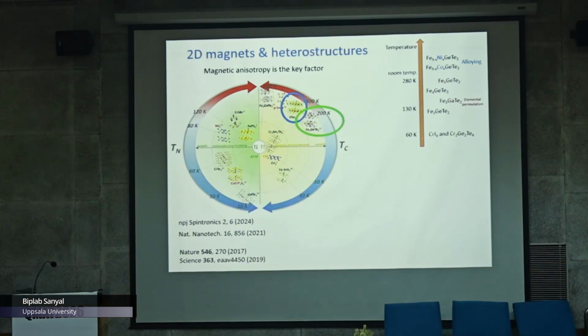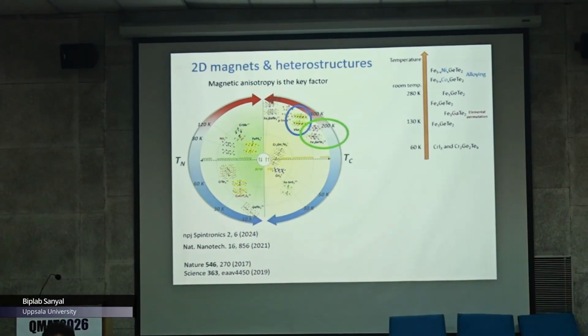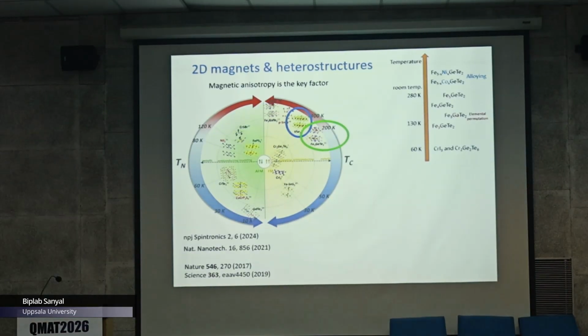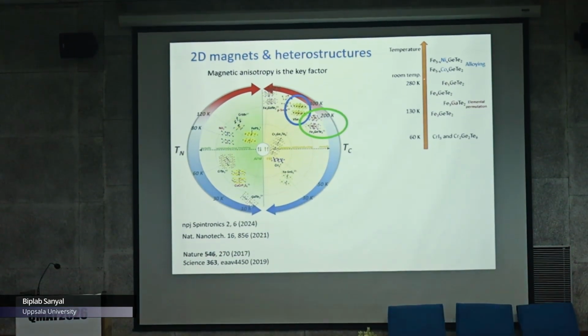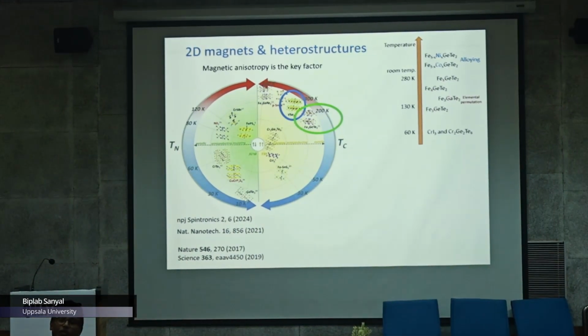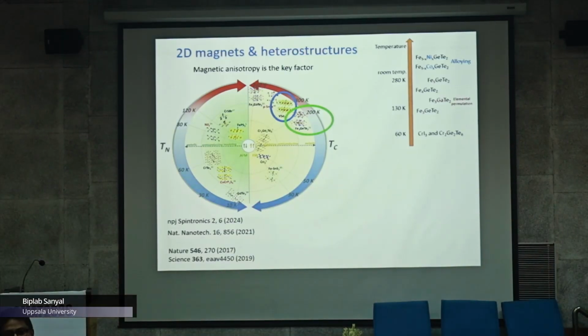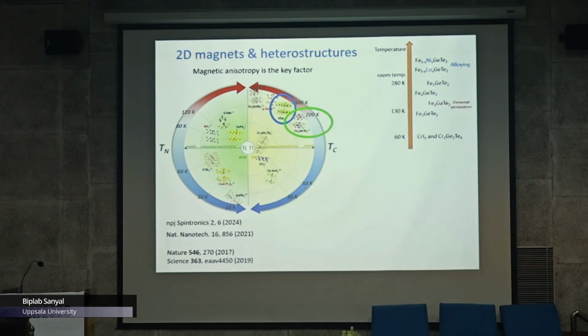the evolution of some metallic ferromagnets. The Curie temperature of these metallic ferromagnets was pretty high. Specifically, you see this iron germanium telluride. These metallic ferromagnets have a Curie temperature close to room temperature, and you can even increase it by alloying. There are some papers showing that if you alloy with cobalt or nickel, you can increase the Curie temperature to a very high value, like even 550 Kelvin or so. So one can understand that this field is very interesting if you can have a room temperature or higher material with nanoscale dimensions, and this can be extremely important for devices and things like that.